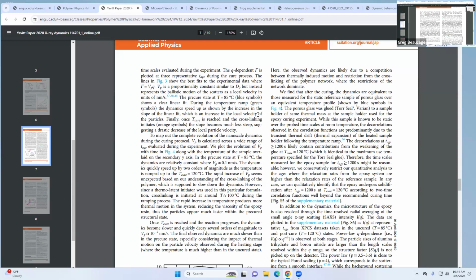So most of what we do in these experiments is test the dosage of photons that we're giving to the sample. Sometimes we'll do an experiment and just fry it, and the dynamics we see won't be representative of our material. You can artificially cure things. You can destroy polymer chains. You can do all these things.